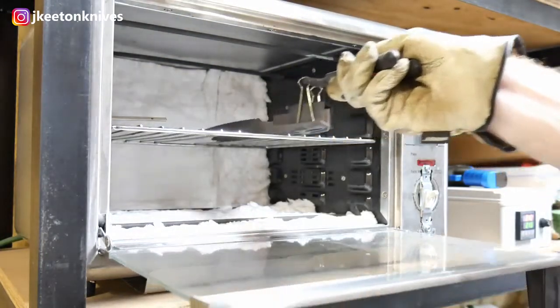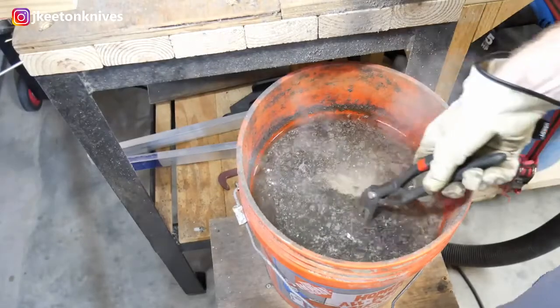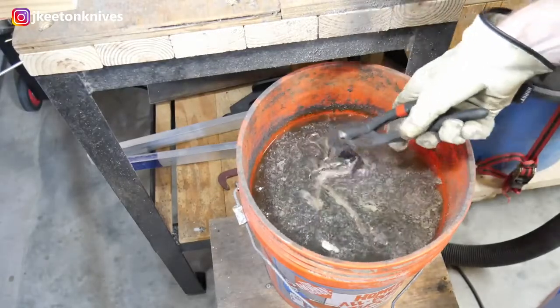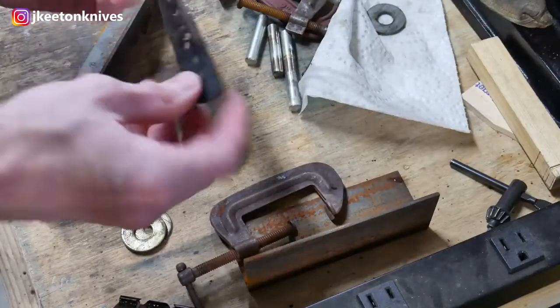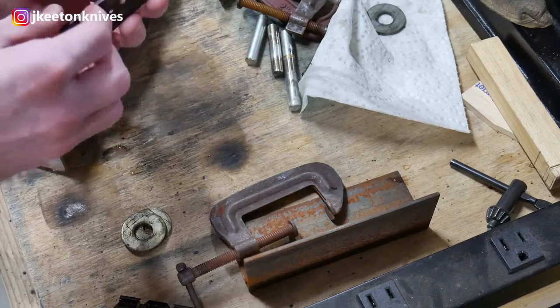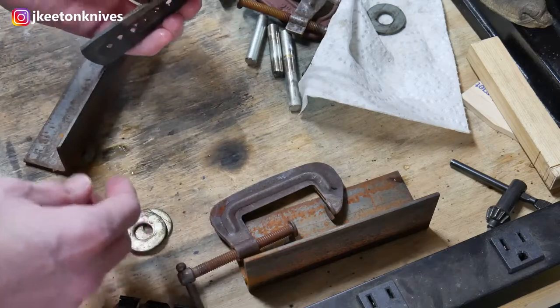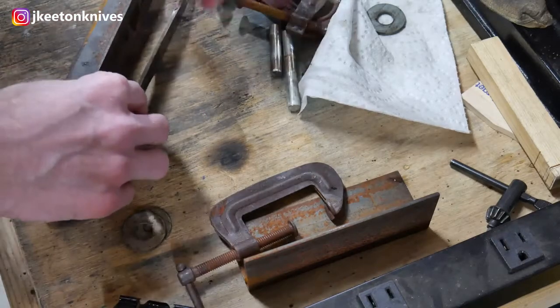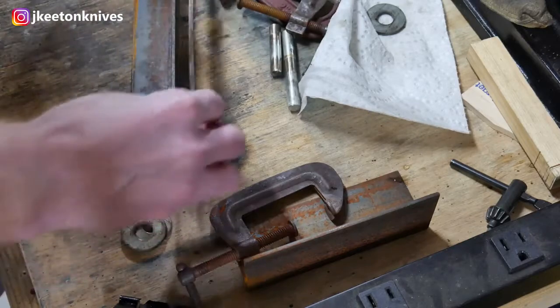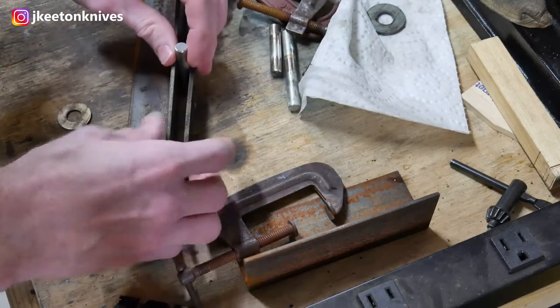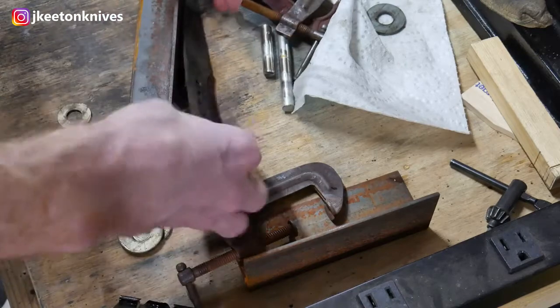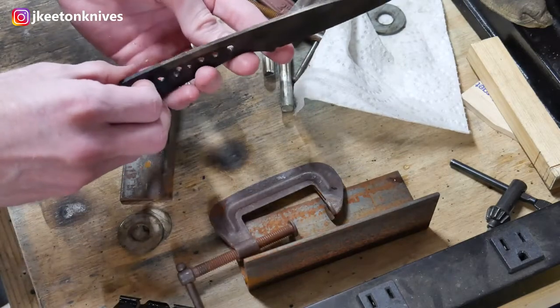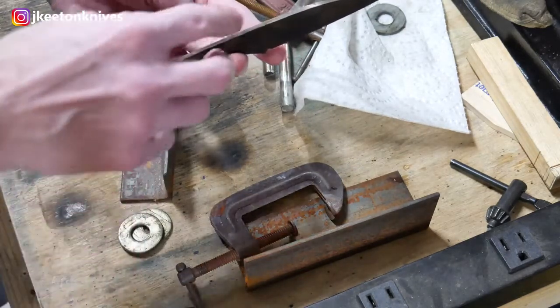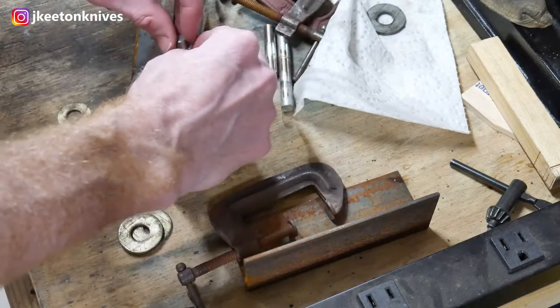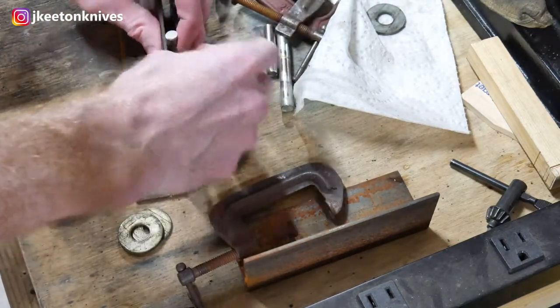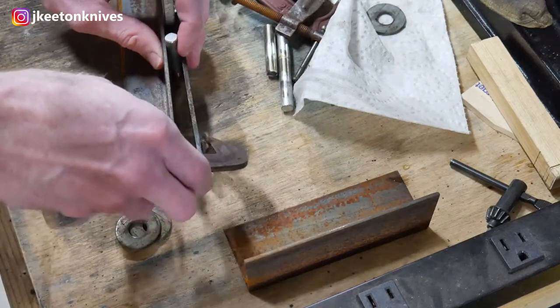Okie dokie, so tempering cycle number 1 has been completed. We'll bring it down to room temperature in my nasty slop bucket here. Then we're going to address the warp. So we have a warp in this blade. To address this warp, we are going to counter bend it against the warp during the second tempering cycle. I've seen this work a couple times. It definitely helps, every time. So make sure you're doing this in the second tempering cycle though, because the last thing you want to do is try clamping up your blade and breaking it before your first tempering cycle. The blade is really hard after the quench.